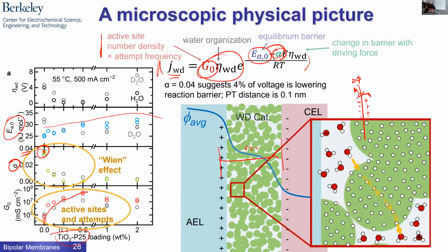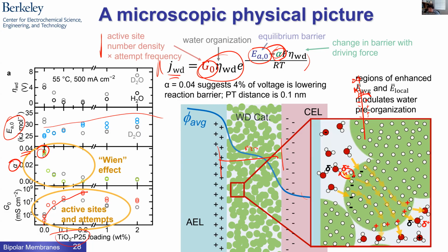Okay. So we can look at this at more of a level of microscopic detail we could imagine. So certainly the TiO2 particles have lots of protons on the surface, OH groups, they're OH groups really, or protons sitting on a bridging oxo or whatever. And these are all communicating with each other, right? They're all hopping around in thermal equilibrium. And any one of those sites can exchange protons with water. So, of course, even at equilibrium, we'll have lots of protons hopping on and off the surface. Okay. So now when I polarize this device, adding more electric field, what's going to happen?